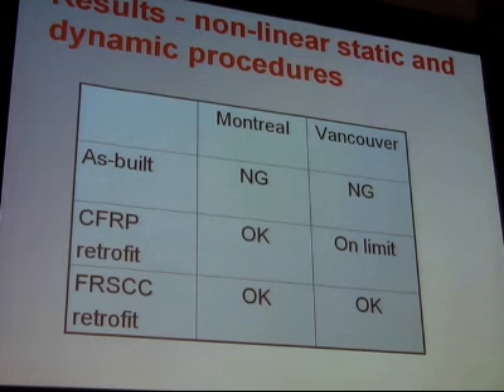For the as-built condition, the structure is no good. It doesn't have adequate performance for either Montreal or Vancouver. And when we performed the CFRP retrofit, which is a very easy retrofit procedure to accomplish, it was okay for Montreal, but it was really on the limit for Vancouver. And it was questionable as to whether you would accept that or not. And of course, with the fiber-reinforced self-consolidating concrete retrofit with that protected zone at the base of the wall, it was okay for both Montreal and Vancouver. These are the results for the 2% in 50 years.